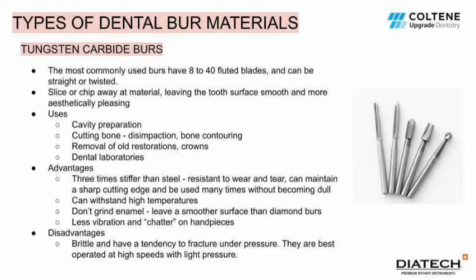Their advantages are that they are 3 times stiffer than steel, which makes them resistant to wear and tear and makes it so that they can maintain a sharper cutting edge and be used many times without becoming dull. They can withstand high temperatures and they don't grind the enamel, leaving a smoother surface than diamond burrs. They also have less vibration and chatter on handpieces. On the other hand, tungsten carbide burrs are brittle and have a tendency to fracture under pressure. Thus, they are best operated at high speeds with light pressure.